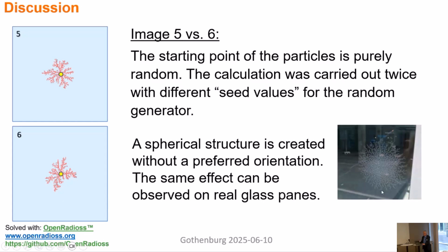And this is also what we are observing in reality here, as a photo from a glass. So this spherical structure is created without preferred orientation. The same effect can be observed in real glasses. Like we took a photo here from this part. There's also a larger project now ongoing in civil engineering using this approach to test it.